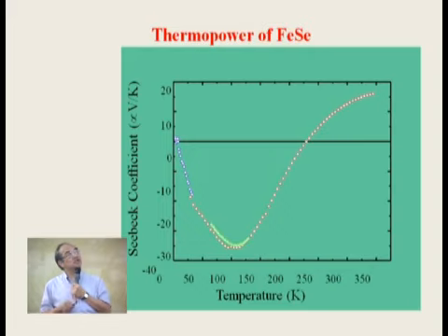And this is the sample we measure by cooling down. And you see that at about 230, 240 degrees, there is a sign change from positive to negative. So that indicates something going on here. If you are a solid state physicist or chemist, then you know it is some kind of band crossover from one band to the other band.